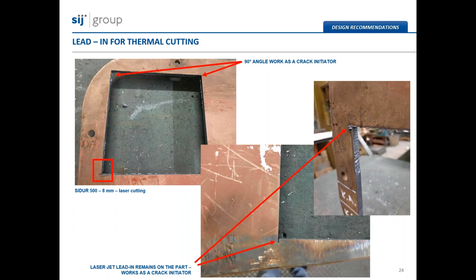We can see two main failures. The first one is the so-called lead-in or start point of the cutting. As you see, the lead-in of the laser jet remains in the part and therefore can act as a crack initiator. The second one is the 90 degree angle at intersections of straight lines. So if possible, and in this case it was really possible, please use circular shapes at those intersections.